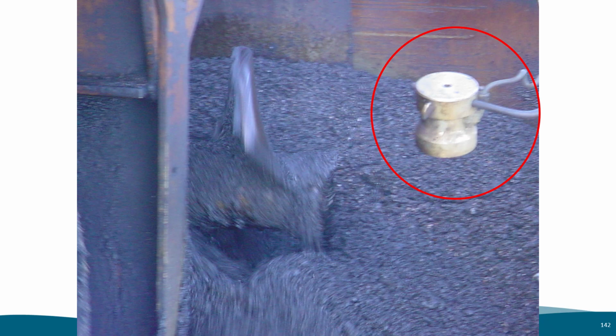This is an image of an auger sensor. It behaves like the auger paddle. Some paver operators don't like this sensor due to the polymer strings that can get gunked up. When this happens, the sensor will not operate as well. The sensor's job is to send information to the paver to know the height of the material in the augers. Overfilling the augers can be as challenging as underfilling the augers. It is important to have a steady flow of asphalt across the roadway and paver width.